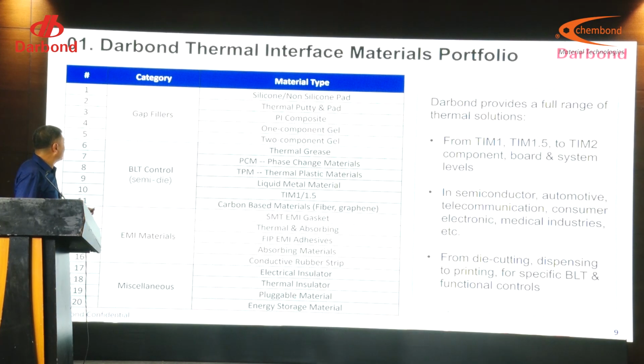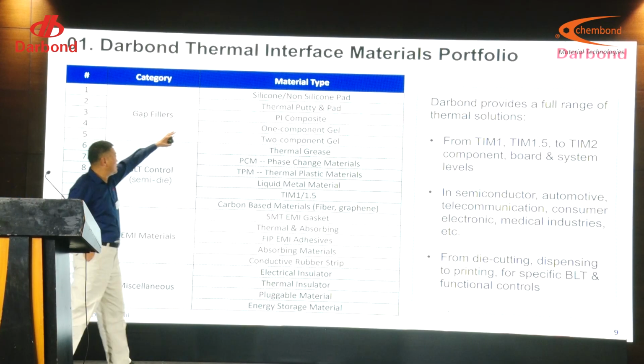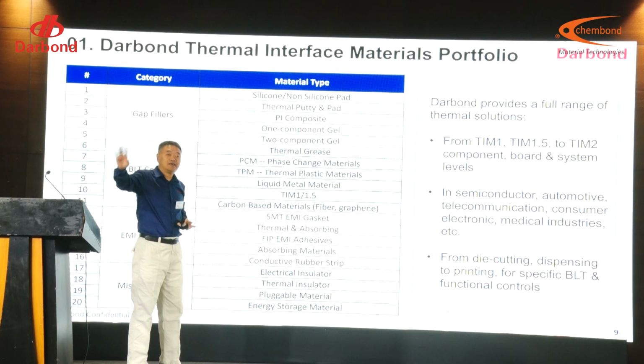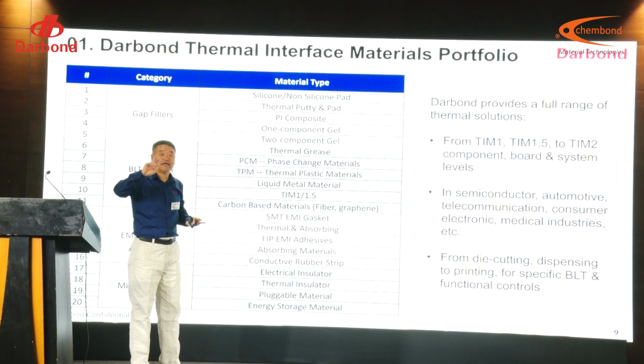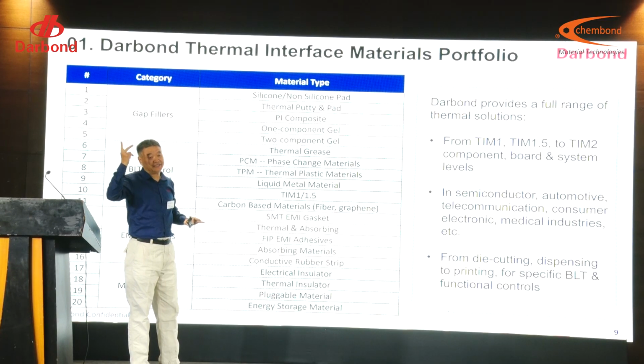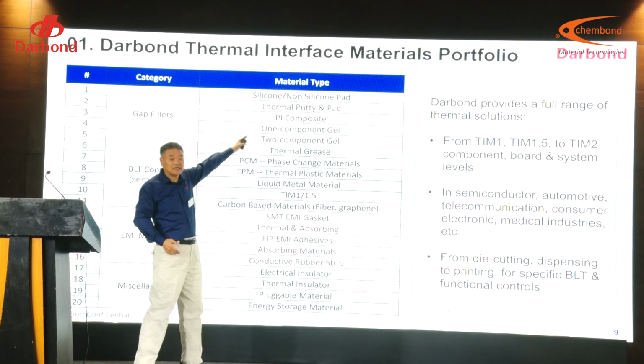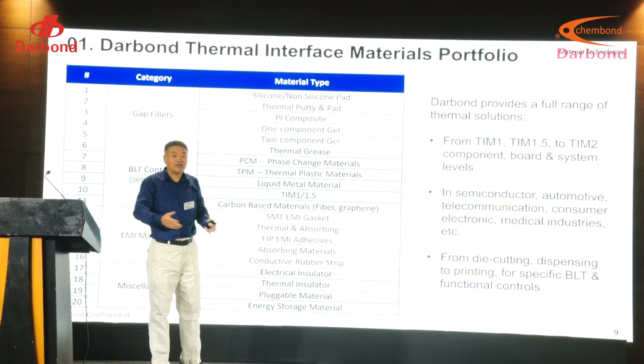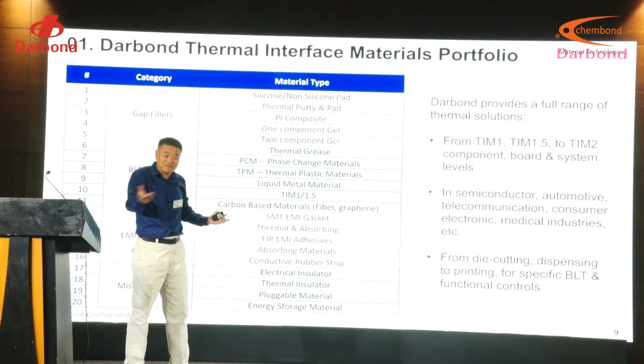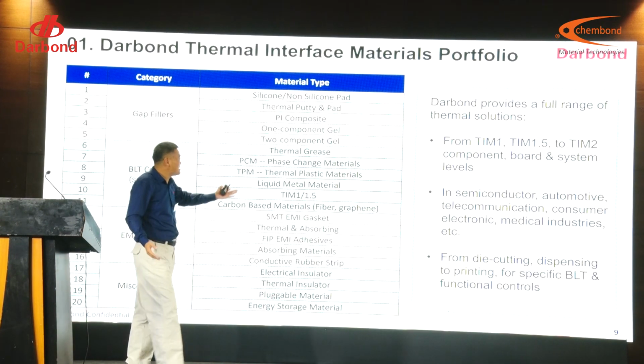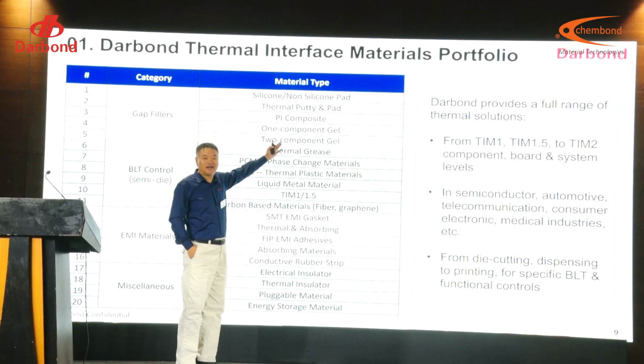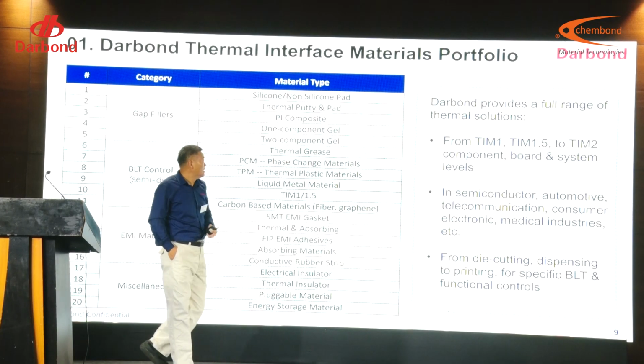Okay, this is the portfolio we provide. Basically, the gap filler, as I mentioned, silicone or non-silicone, because the silicone elastomer always has high contact resistance. You need a softer material. That's why we provide the putty. Putty, you can use the putty itself, or you can use the putty pad, right? And you need some carrier. You can use the polyimide carrier.